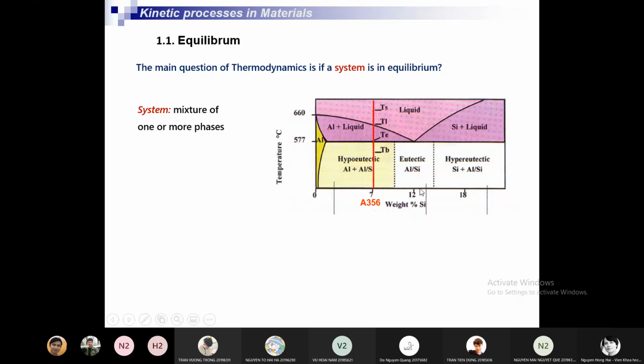It's about 12% of silicon. So before this composition, we have a hypoeutectic alloy. For example, alloy A356 with about 7% of silicon. So for this system, for this alloy, we have the microstructure like this. We have a primary aluminum like this. It's dendrite. In the form of dendrite.